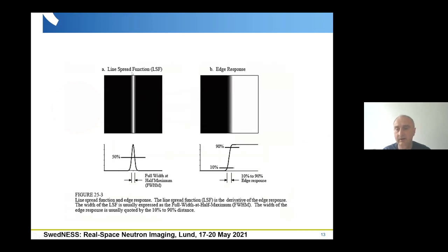If we have a line spread function or edge spread function, actually the measure for the resolution is the edge response here between 10 and 90% of intensity. And this is a measure for the resolution. If we take the first derivative of this one, we'll get also the line spread function, where the measure for the resolution will be just the full width at half maximum. So this is just one impression of how the resolution can be measured. This means that if you have a sharp edge, you can put it in the beam, and after analyzing the profile through this edge, we can get some first preliminary estimation for the resolution.